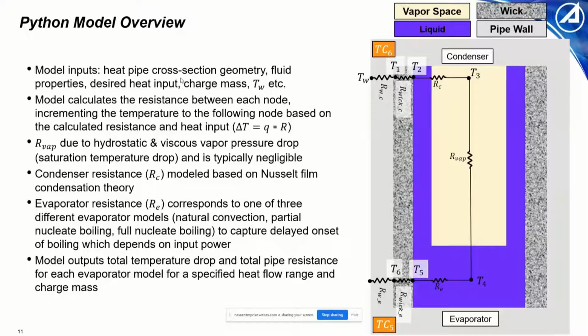The basic formulation for the code is the model calculates a resistance between each node. So it starts at TW, it would calculate a conductive resistance between TW and T1, and then from knowledge of the heat input and the individually calculated resistance, we can calculate a delta T between each node. Moving from T1, we know the calculated resistance, can calculate a delta T between TW and T1, and then same thing, you know T1 now, calculate a conductive resistance through the wick, calculate your delta T, then you know T2, and it marches sequentially down the line there.